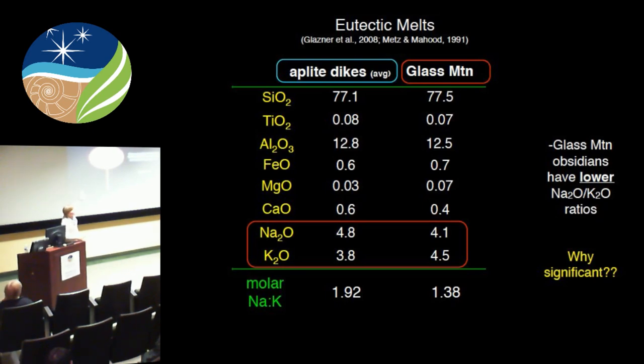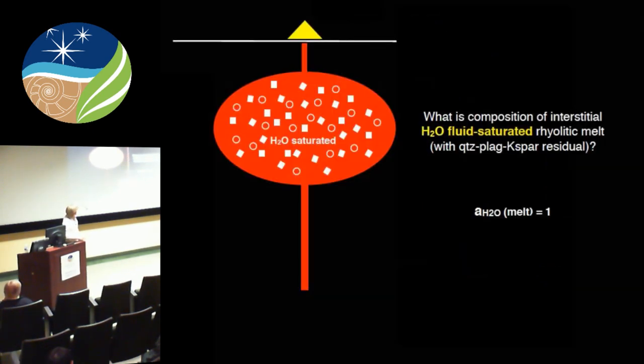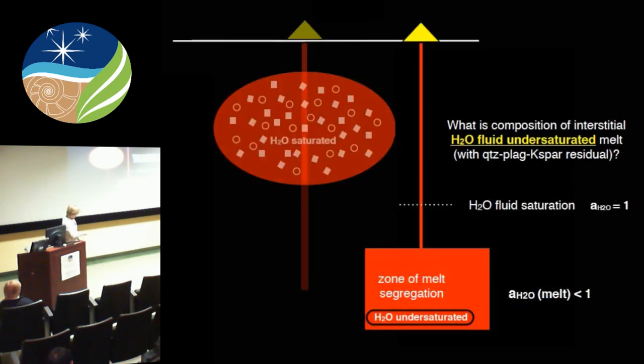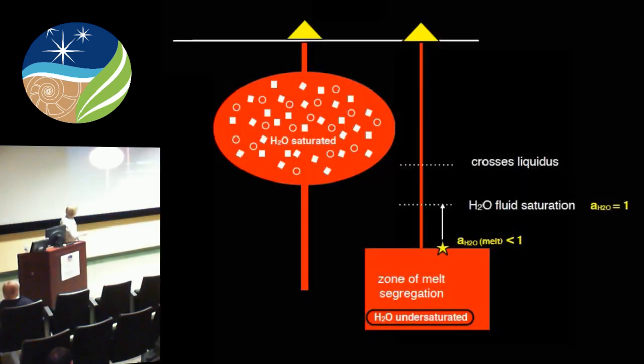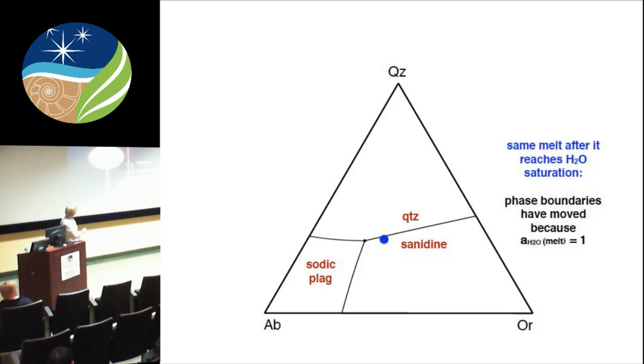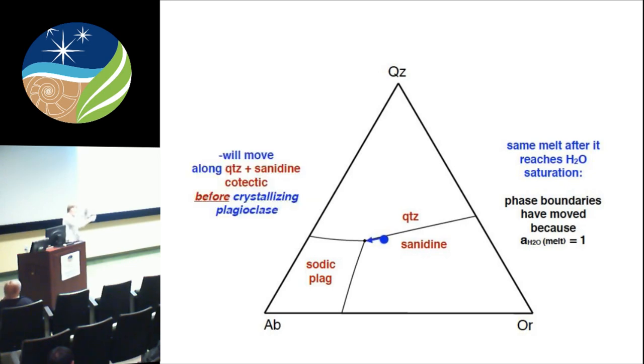So we know what happens when the activity of water is 1, right? It freezes. But what happens if we're deeper and it's undersaturated? The activity of water is less than 1 and the melt starts to segregate out. It's going to have a composition here relative to there. Then it rises and hits fluid saturation. At the point saturation is hit, the activity is 1. So all of a sudden, it finds itself not at the eutectic, but along the cotectic. Then when it continues to rise and crosses its liquidus, it's going to do cotectic crystallization of sanidine and quartz. Remember the 3:3:1 proportion we saw in the Bishop Tuff. Then it hits plagioclase and then chokes up.